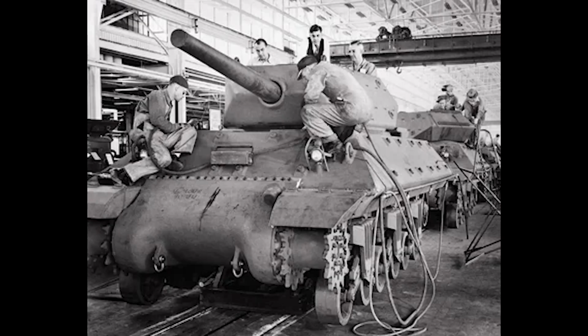American testing in 1942 and 1943 had demonstrated the quality of this armor. Test firings using 75 mm guns showed that American rolled homogeneous armor was 10 to 20% more resistant than cast armor of the same thickness. The rolled armor could be brought to higher hardness levels without becoming brittle.